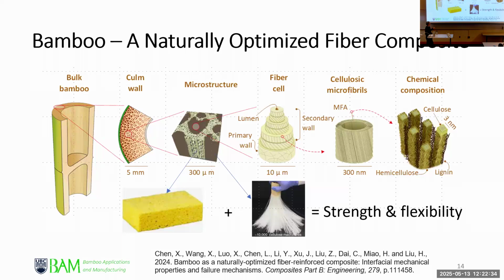And then you're going down to the cell itself, and the number of layers is actually quite different, and the structure of layers is quite different from wood. It has multiple layers, up to 8 or 10 layers, whereas wood you got S1, S2, and S3. And it's also up to 3 layers. And then the microfiber angle is the same thing. We bring it down further. You got the chemical composition, which is cellulose and hemicellulose and lignin, which is more similar to a hardwood than softwood.